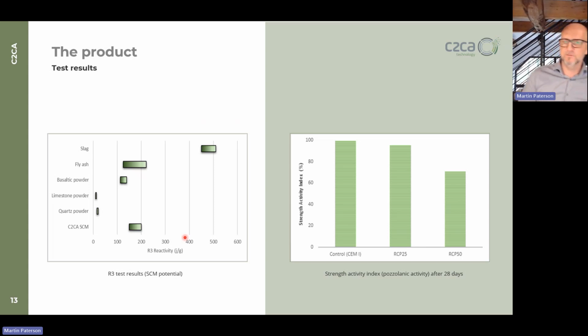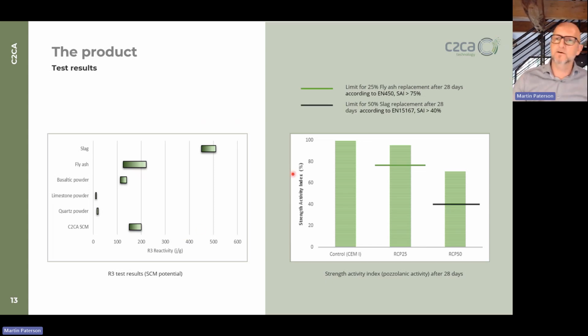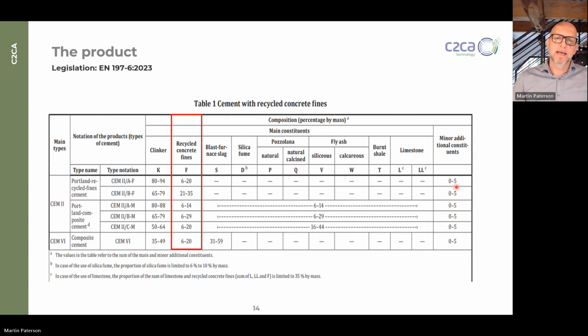And good properties have also been shown in the strength activity test. So you can see here the limits which are needed for fly ash replacement and for slag replacement, and our material has been well above that. So it's suitable to be a good SCM, and that's proven.